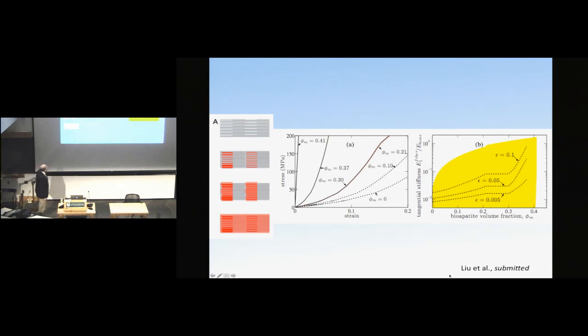is a combination of a very stiff region, the mineral is stiff, with a very compliant region. And the addition of more stiff material to the stiff region still won't prevent the deformation from localizing in the compliant regions. Then thereafter, there's a more rapid stiffening as the mineral grows to encompass the regions that do not have internal mineral. So as the mineral grows over the compliant phases, the stress-strain response ramps upwards, and then finally there's a sudden spike at the very end to the stiffness of bone.